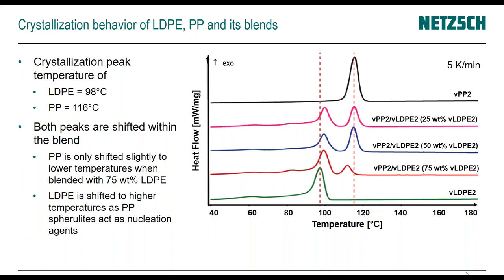And just by, how is that called in English? Sorry, by just putting your peak of the pure material as 100%, you can calculate what the peak in the blend equals in percentage to that. And then knowing the weight, you can calculate out of the percentage the actual weight proportion. I hope that was clear enough.